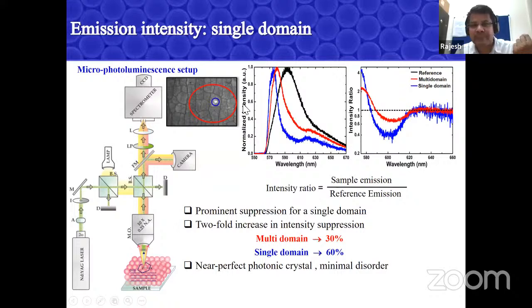So in the blue curve, the emission is collected from a single domain of the photonic crystal. You can see that around 60% of the spontaneous emission is suppressed in intensity. Okay, so when you go from a large area measurement to a single domain measurement, you can even get close to 60-70% suppression, even though these samples have very low index contrast, because the samples are made using polymeric material. So the refractive index variation is quite small. So we don't expect too much change, but because of the careful measurement, we could get this kind of emission suppression. Now the question is, do you get the same suppression everywhere in the crystal?